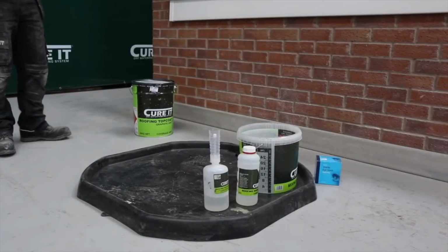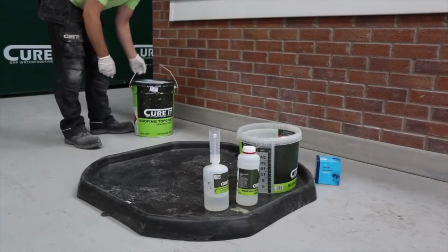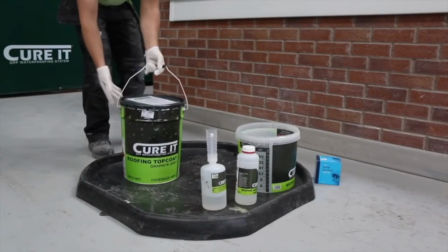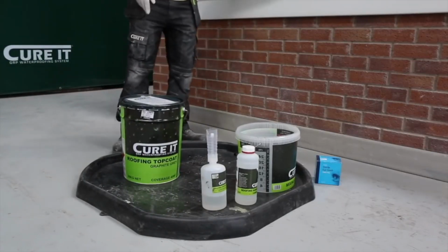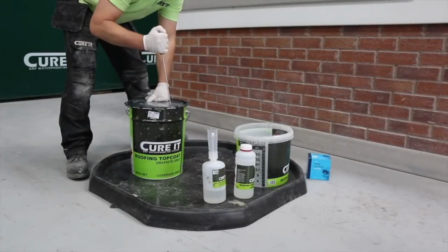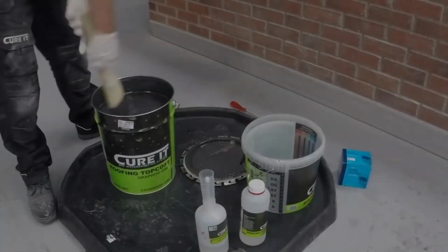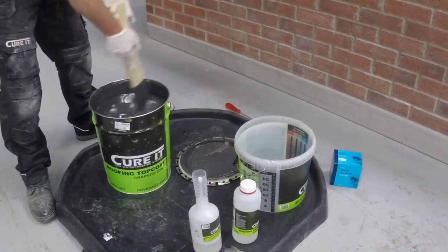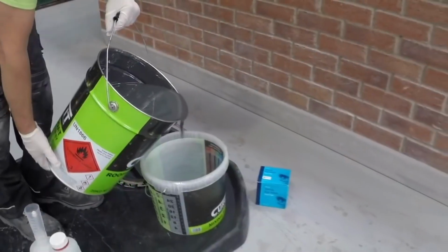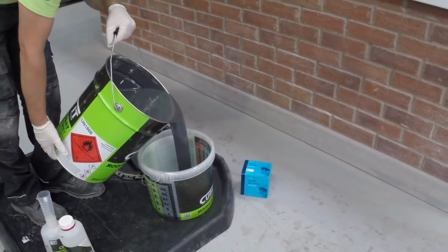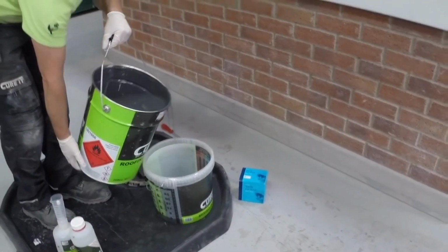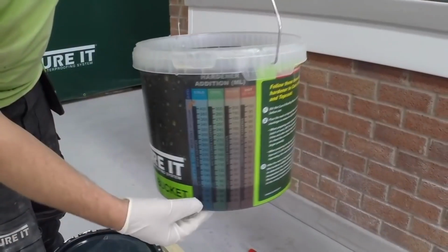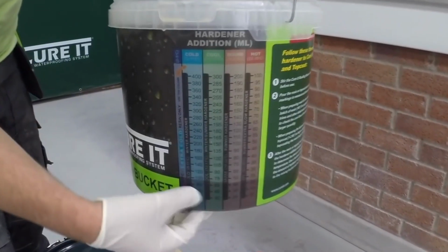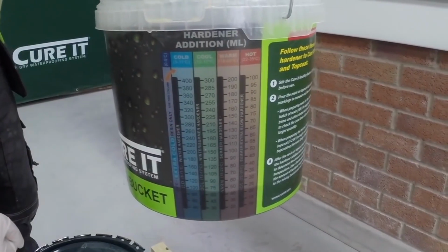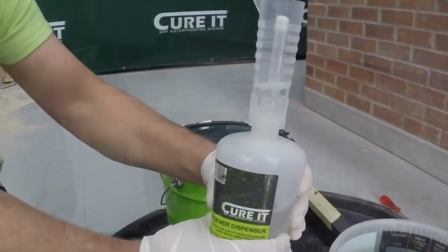Use a cement mortar mixing tray as a bund for decanting and mixing of top coat, ideally off the roof if possible. Using the lid opener tool, open the can of top coat and mix well with a slate batten before pouring the top coat into a Curit mixing bucket. Ensure you are wearing safety goggles and gloves, and eye wash is available in case of an emergency. Using the hardener addition chart on the side of the mixing bucket, measure out the required volume of hardener using the safety dispenser and mix into the top coat using a slate batten for a minute.